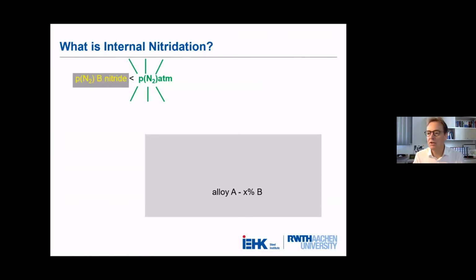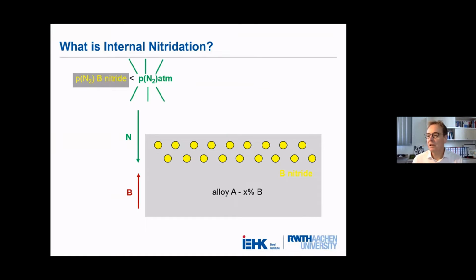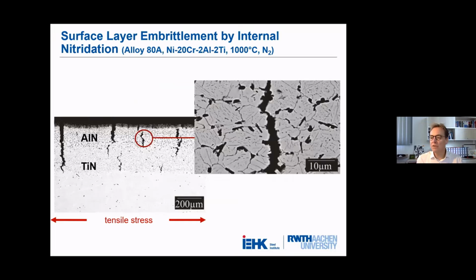Internal nitridation is essentially the same. We have the situation, and sorry, that must be the other way around. If the equilibrium partial pressure of B nitride is lower than the nitrogen partial pressure, then we will get the formation of internal B nitrides. The nitrogen diffuses inwards and then forms B nitrides. Again, here you can see an example of a nickel-chromium-aluminum-titanium alloy, and also here you see the internal nitridation attack.